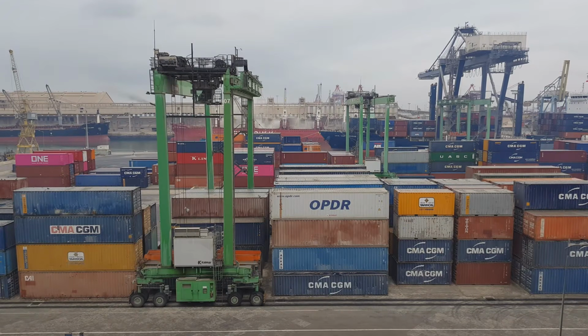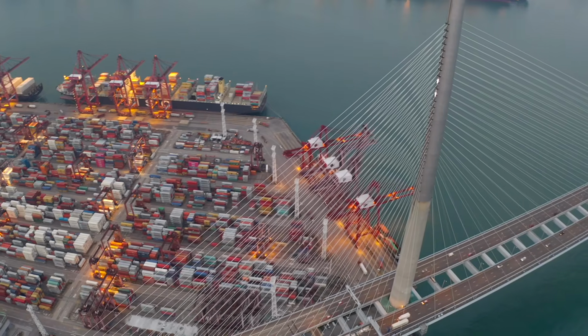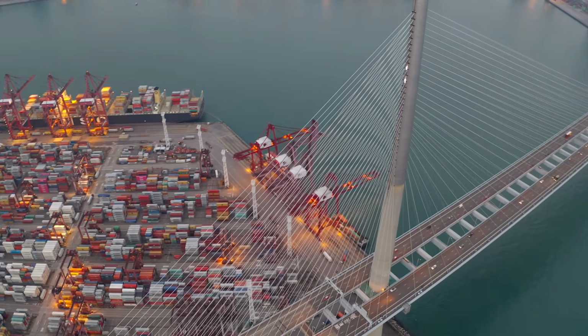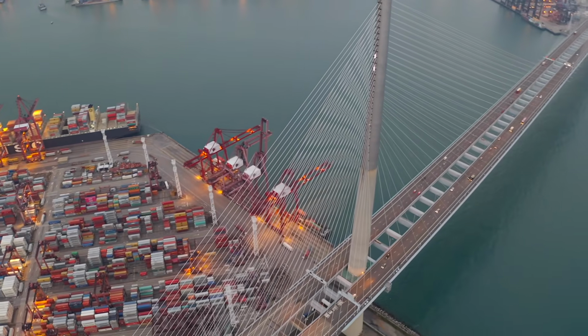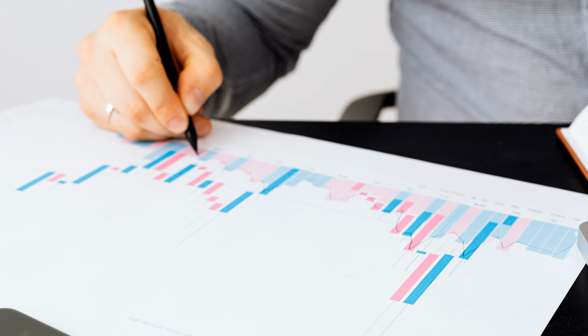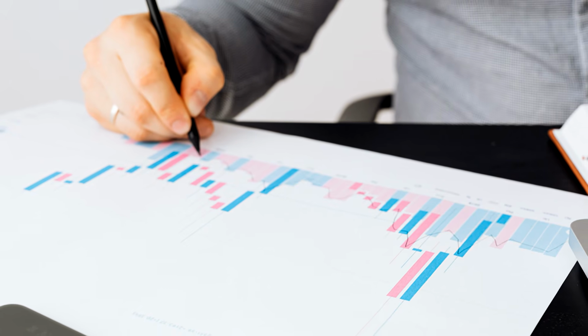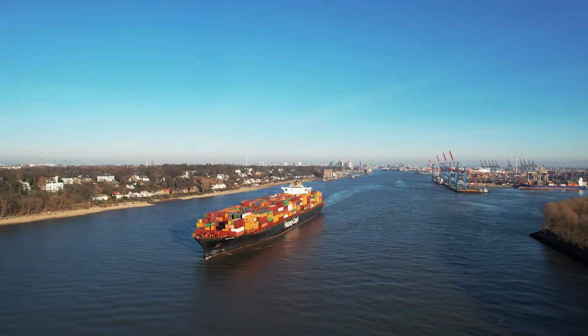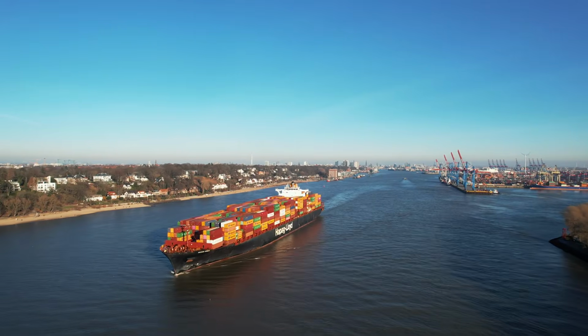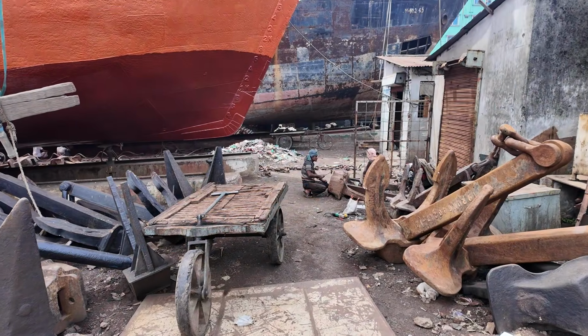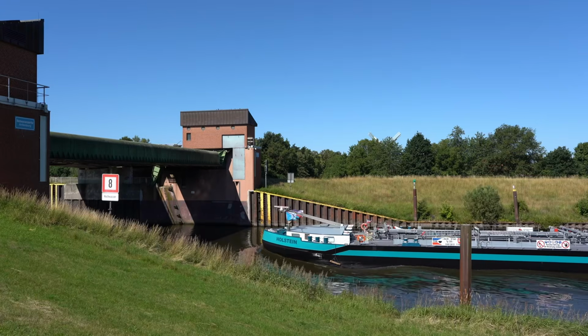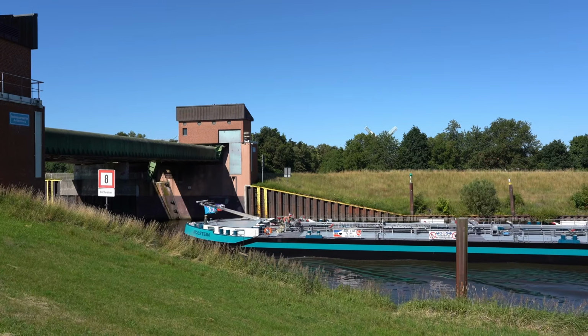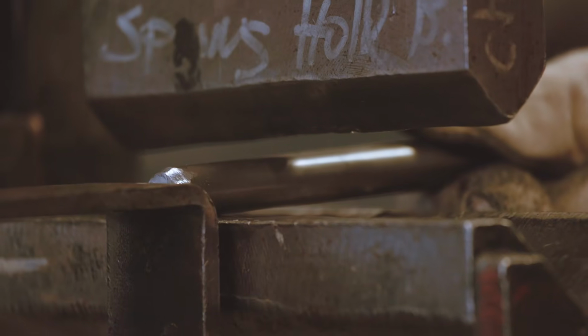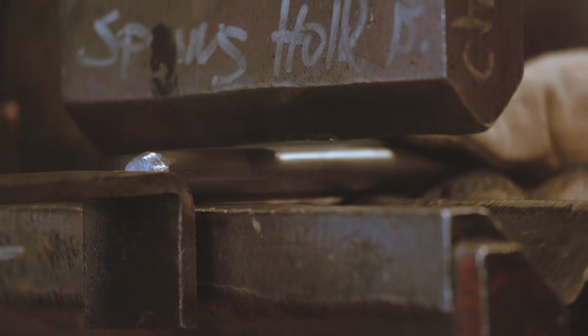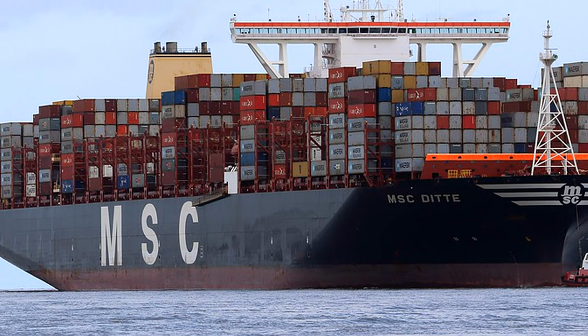From the ship's loading condition, the estimated sea state, the construction records, the material certificates, the as-built drawings, and detailed structural modeling. The Class NK Committee on Large Container Ship Safety published its findings in 2014. The Japanese Ministry's report followed in March 2015. The conclusion was that the hull girder fracture probably resulted from buckling collapse of the bottom shell plates in way of a butt joint in the double bottom structure underneath number 6 cargo hold. In the midships part of the ship, the bottom plates buckled and collapsed first. The girder fractured afterwards, in a short time.